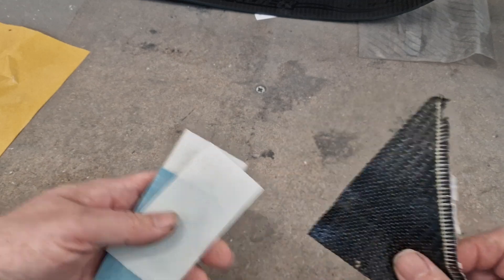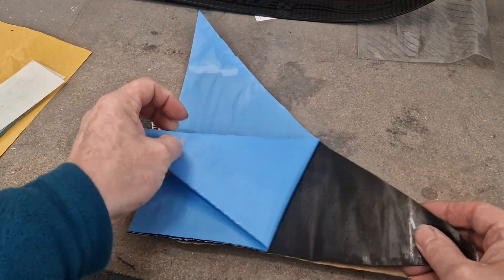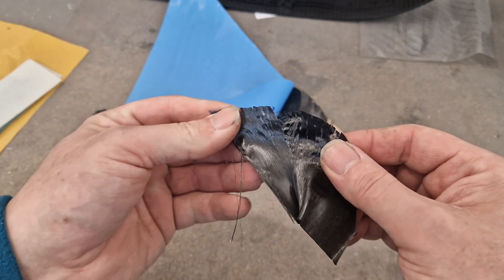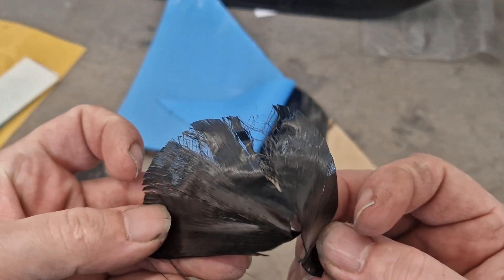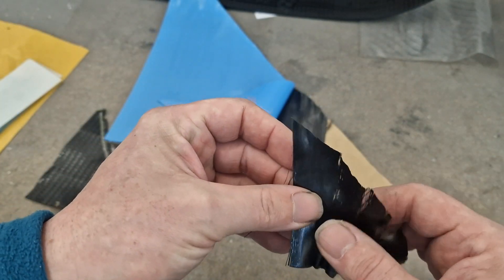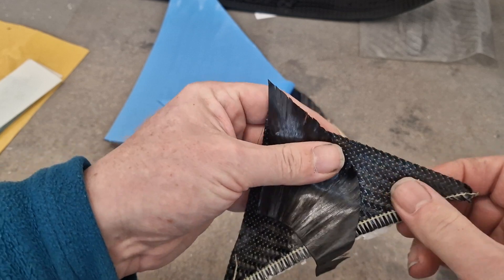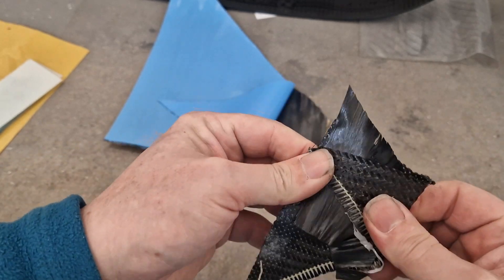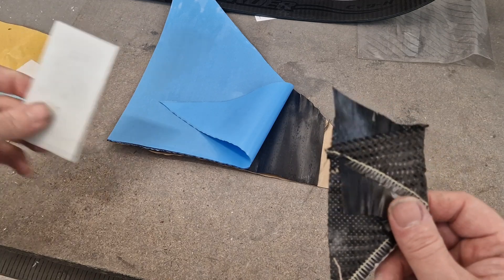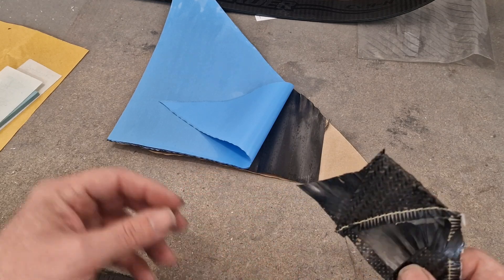So rather than using unidirectional glass to make your limb, what you could do — and here you can see — you've got unidirectional carbons. There's unidirectional carbon: it's all microscopic little fibres of carbon fibre, and that stuff really changes things. So what you would do is take your 45-degree layer, take your unidirectional, lay it up, cure it, and that would be your laminate — because you'd have your unidirectional carbon inside there. And that would weigh a ton less, and that's where the speed gain comes in, that's where the light mass limb comes in.